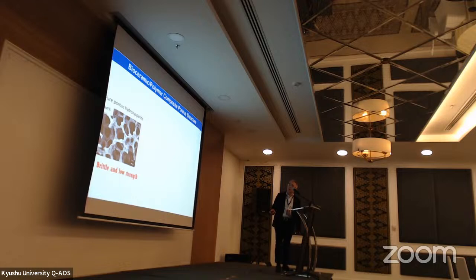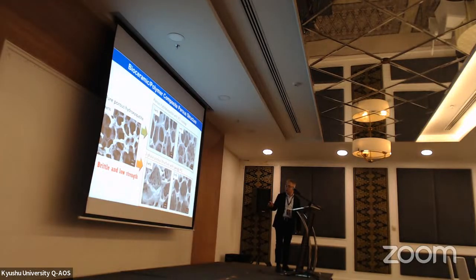Now we can fabricate this kind of very unique porous structure using hydroxyapatite. However, this structure shows very brittle fracture behavior and very low strength. That's why I'm trying to improve the mechanical properties by introducing a polymer phase. The upper part is porous hydroxyapatite with PCL coating. PCL is a biodegradable polymer of medical grade. The second one is a two-phase porous structure with spongy PCL: hydroxyapatite porous structure with polymer porous structure.